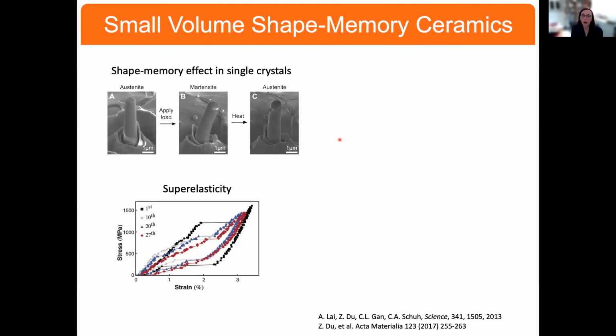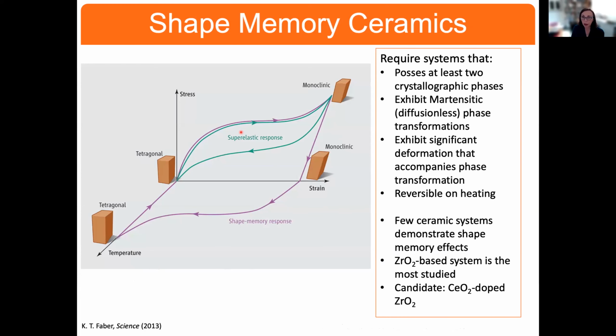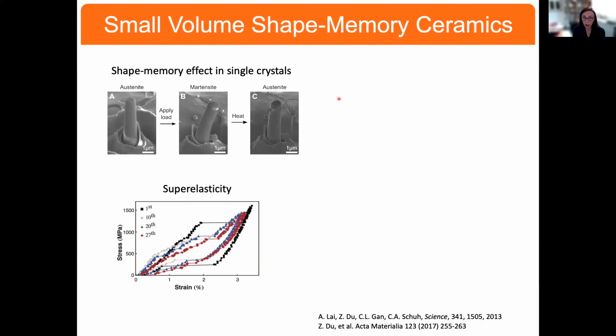Okay, so there was work in the late 1980s that tried to produce these materials in bulk, and the problem was that the volume changes associated with this were so large that the materials would just crack as they go through these transformations. So the work was dropped, and it wasn't until the mid 2010s, so 2013, 2017, where people started making pillars of these materials to study them.